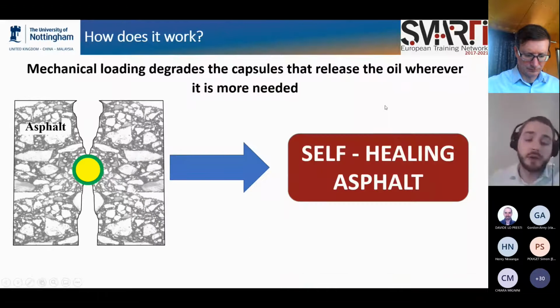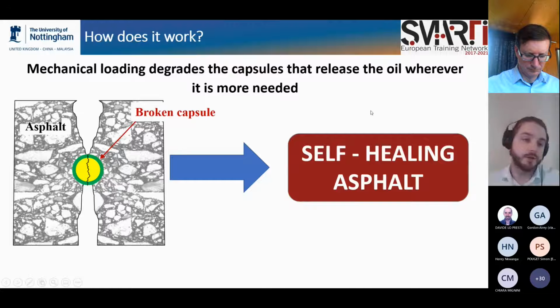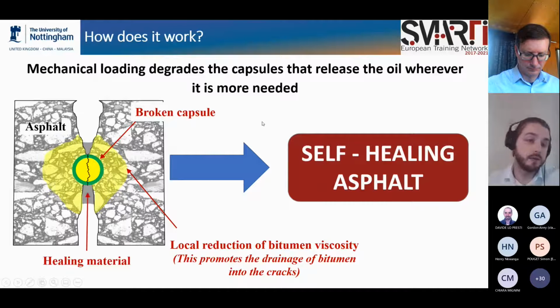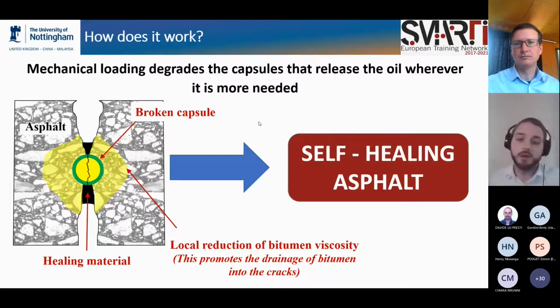So the idea of the encapsulated bitumen rejuvenators is based on the addition of some encapsulated bitumen rejuvenators, in our case sunflower oil, inside of the asphalt mix. And when the cracks appear on the asphalt because of the traffic loads and the weather conditions, these capsules break. The capsules located in the most stressed area break and release the sunflower oil. And this sunflower oil reduces the viscosity of the bitumen, makes the bitumen flow into the crack, closing the crack.